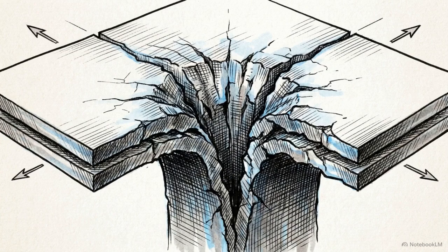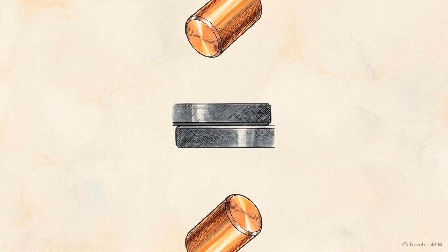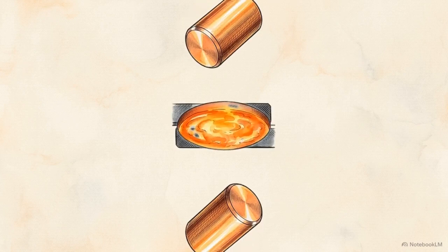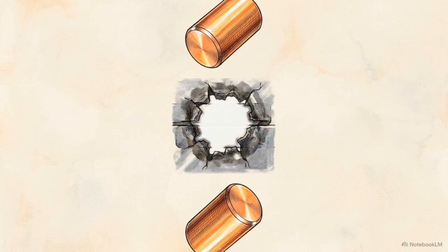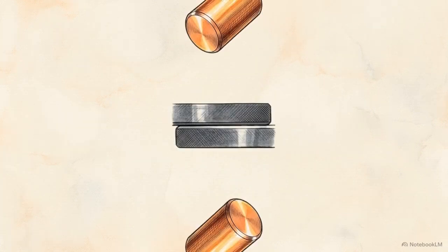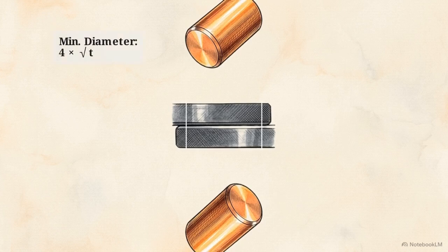When that delicate balance of current, pressure, and density fails, the system produces specific physical defects that compromise the assembly. The most violent failure is expulsion. The internal pressure of the molten metal rapidly builds until it overcomes the clamping force, breaches the clamping boundary, and sprays liquid metal directly out from the faying surface. This happens when the current is too high or the clamping force is too weak. The molten material escapes, leaving behind a structurally deficient, undersized nugget.